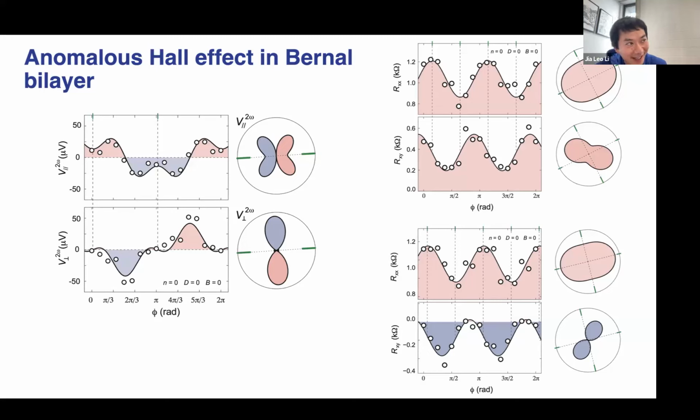Yeah. So that identification comes from the quantum Hall effect regime. You do have to apply either a perpendicular magnetic field or an in-plane magnetic field to identify the state that you mentioned. In suspended bilayer graphene, you can in fact go down to b equals 0. You don't need any perpendicular field, in which case it becomes a fully in-plane anti-ferromagnet.